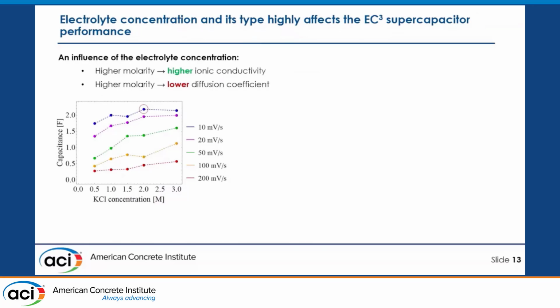And some feedback from our tests: we can see that not only choosing the type of electrolyte, but also its concentration, we affect the properties. We affect the capacitance of our system. Here, KCl solution, different concentration from 0.5 to 3 molar and the capacitance, and we can see that there is some kind of optimization that can be performed at different scan rates, keeping in mind that higher molarity results in higher ionic conductivity, but at the same time lower diffusion coefficient.